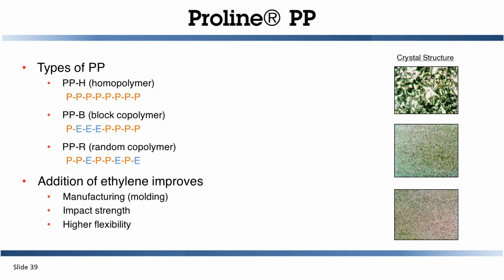For homopolymer, we're limited to really jagged edges, and that's a place where chemicals might attack on a molecular level. By the addition of ethylene, we get a smoother surface area, and that does a couple of things. First of all, it's easier to manufacture, especially in molding. We have fewer voids on the inside of the material, which means a higher end quality product. We have a higher impact strength. We also have a higher flexibility. So it will move more. The downside to that is slightly closer support spacing for the PPR systems versus a homopolymer system.